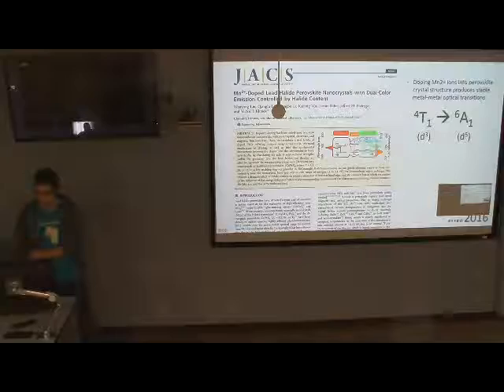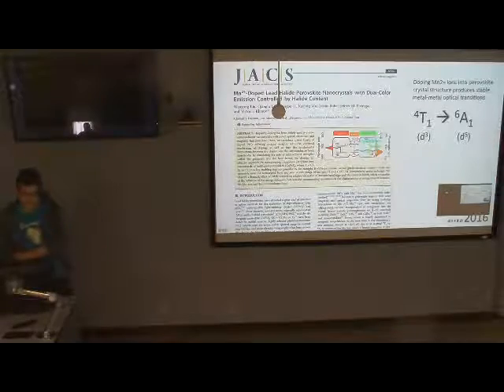And so the first report I can find that looked at doping perovskites with transition metals was from the Klimov group at Los Alamos. And they found that they got a dual emission from the perovskite crystals after they doped them with manganese. So if you look at this panel here, the blue and the green correspond to emission from the regular quantum dot, and then the orange corresponds to emission from the transition metal.